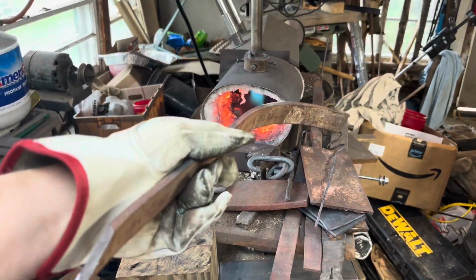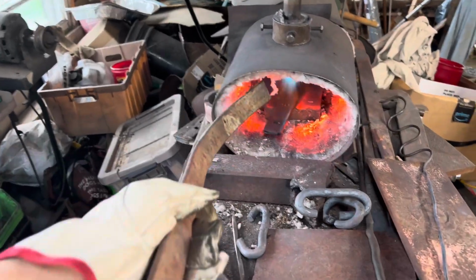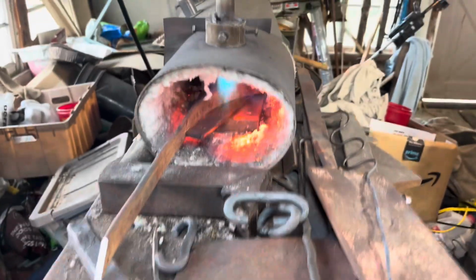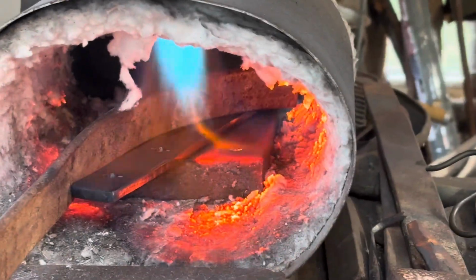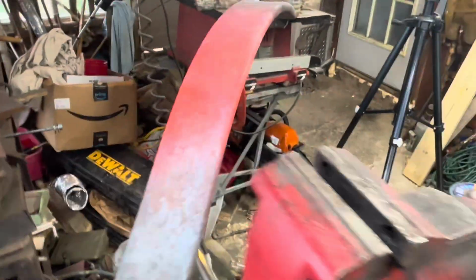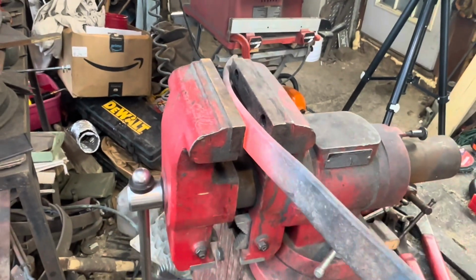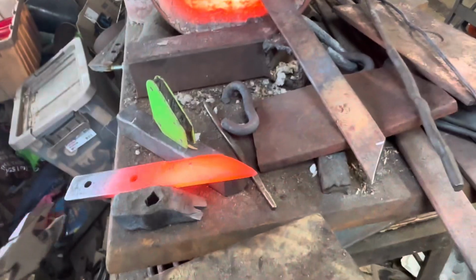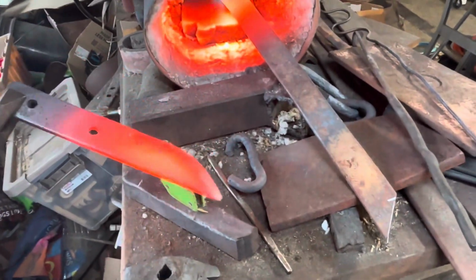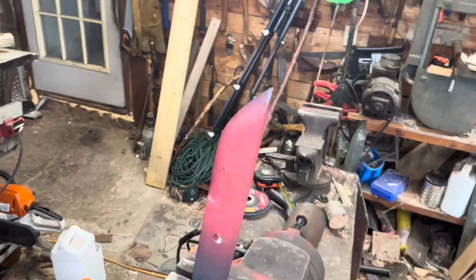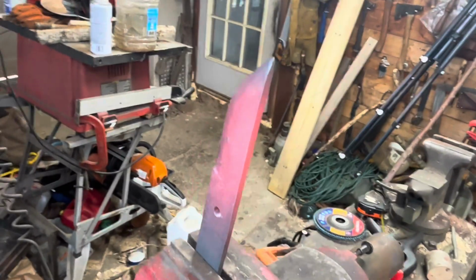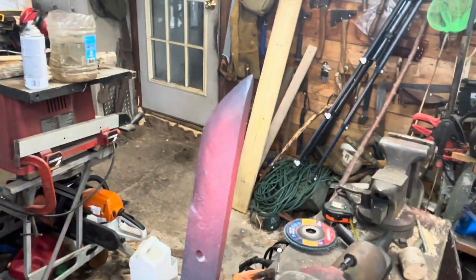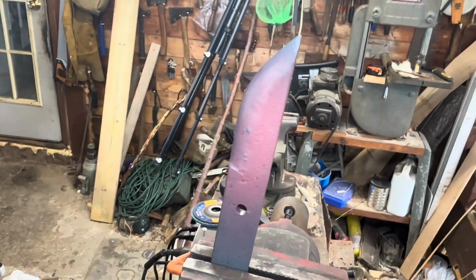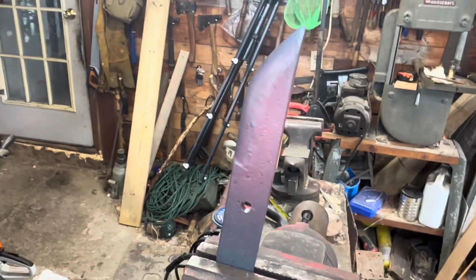While it's heating up, I'm going to straighten out the rest of the piece. This piece of scrap is 18 inches long, so I can get 2 9-inch knives out of it. So I've got to straighten it and flatten it because it comes arched like a leaf spring, and that's kind of hard to do when I'm holding the phone videoing in one hand. While it's non-magnetic, I'm going to put it in the vise and let it air cool to black, and that normalizes the crystal structure. Most people do this 3 times. I'm only doing it once.